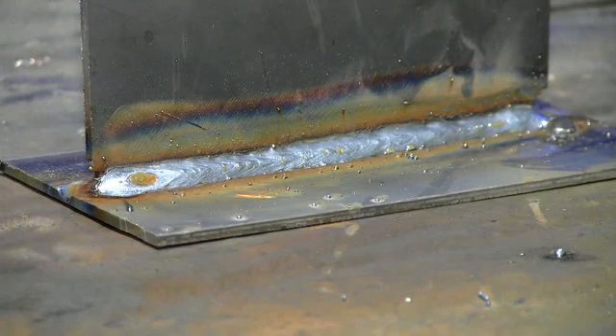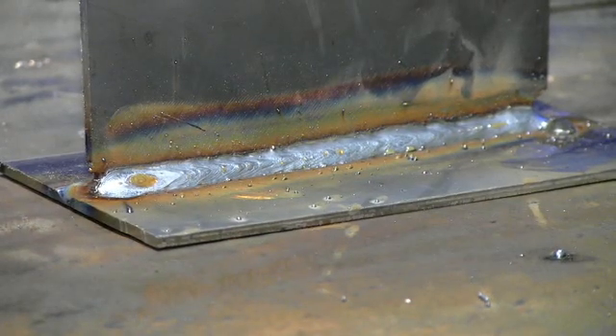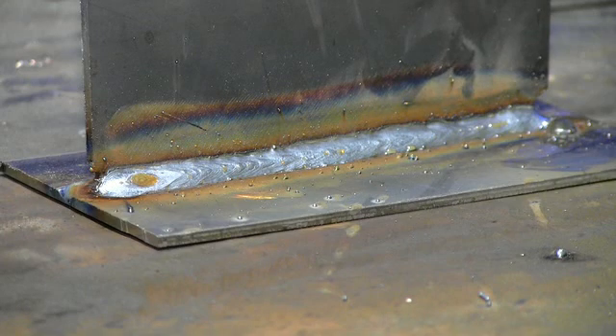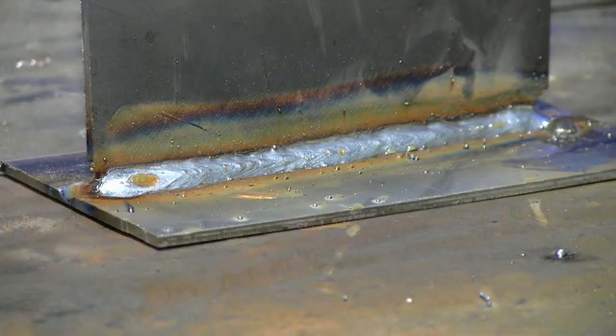Now from that demonstration, you can see that there was much more spatter being generated from the arc. You can see the larger, brighter BBs being expelled from the weld puddle. And those are evident on the finished weld plate. Also, you could hear a much more defined crackling sound with the arc rather than the typical swoosh sound or wisping sound of a spray transfer arc. So those are the big differences, and this was only because of a couple volts drop from our welding voltage.